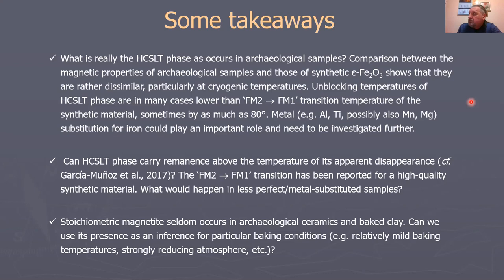Second issue related to this HCSLT phase is that, in light of the discovery of García-Muñoz and others, can it carry remanence above the temperature of its apparent disappearance from the record? And does it really disappear? That also needs to be seen in the future. And I still insist that stoichiometric magnetite seldom occurs in ceramics and baked clay.